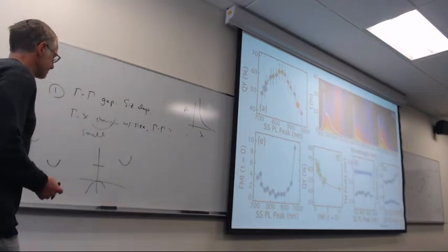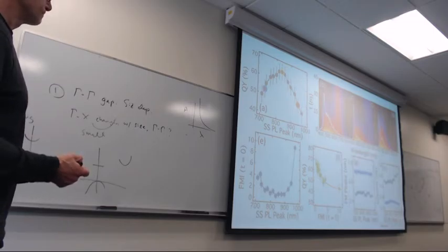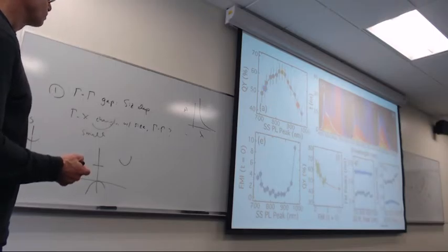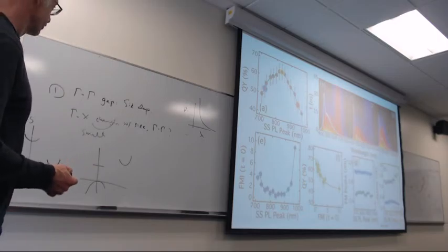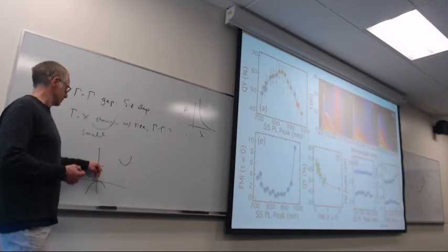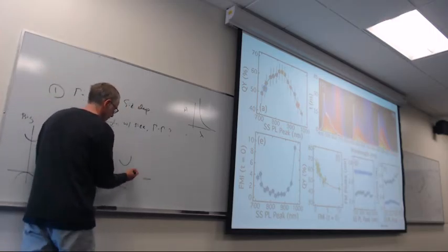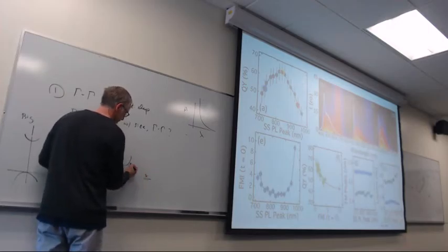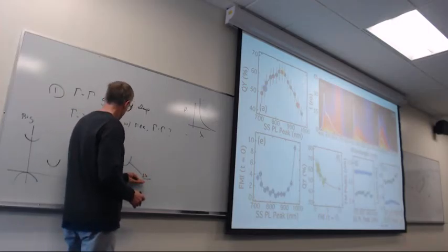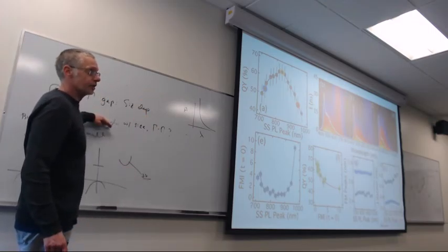You expect that on the surface you might create defects at different positions, and then this defect can technically have a shift in energy, right? Why is it so constant and not dependent at all? That's a good question. Why is it way up here and not in the middle of the gap like it usually is? If it's a surface defect, that usually means dark, right? Yeah, why is it blue shifted, not red shifted? That usually means you got some kind of bad state out here and you end up here and then it goes dark. But this is clearly much, much bigger in energy.